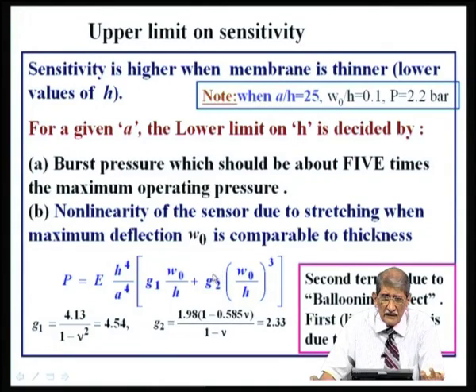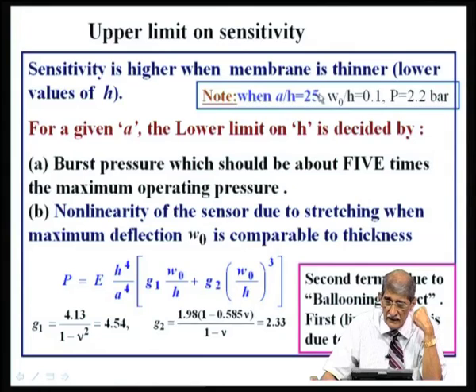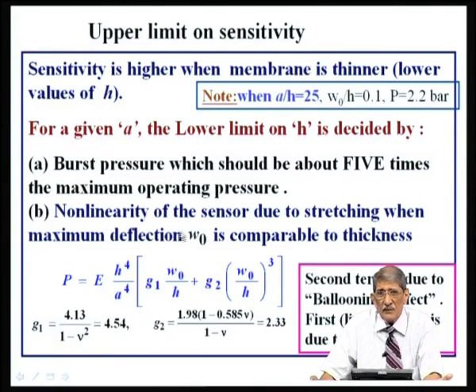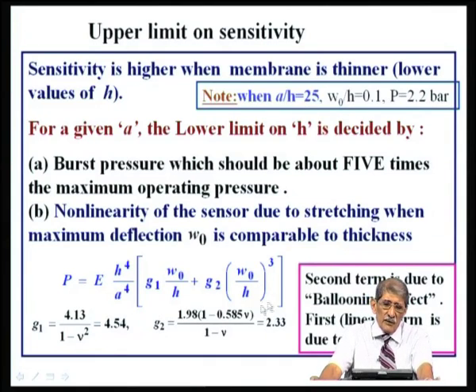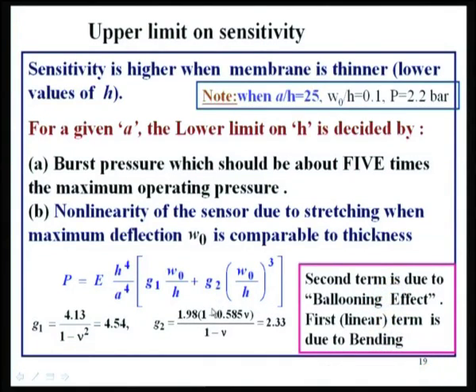In other words, you must stop using the sensor when the deflection W naught becomes comparable to the thickness. So, for this example where the a by h ratio is 25, at a pressure of about 2 bar, the second term becomes comparable to the first term. That means you cannot use it beyond 2 bar, though your burst pressure will be much higher than that. You do not go on using it till burst pressure. So, the ultimate limitation comes from these linearity considerations. Okay.